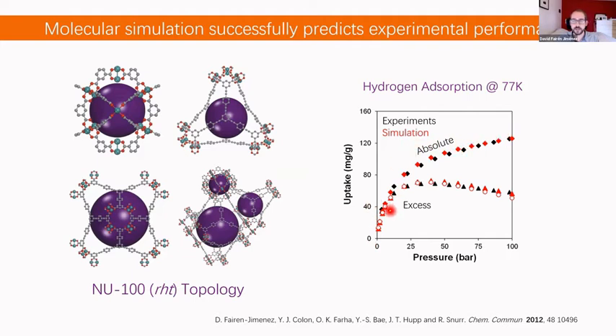Something very important for people who are not familiar with molecular simulation is that we don't run the experiments and then try to fit the experimental data with the simulation. It's not that. What we do is run the simulations, get an adsorption isotherm, and then compare this with experiment. Especially when we work with experimentalists, we do the simulations alone, and then we send the data so they can really compare, and they can realize that we are not adjusting our simulations. It's just pure prediction without any experimental data.